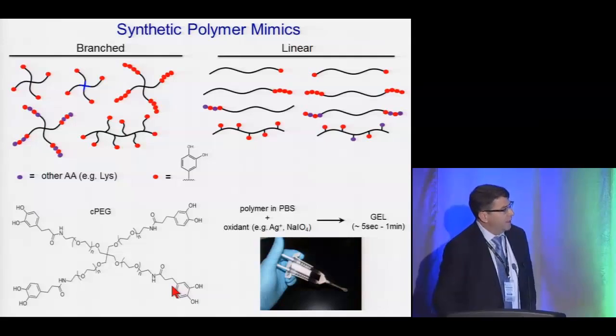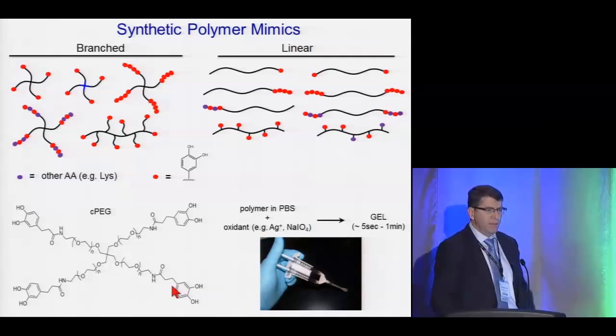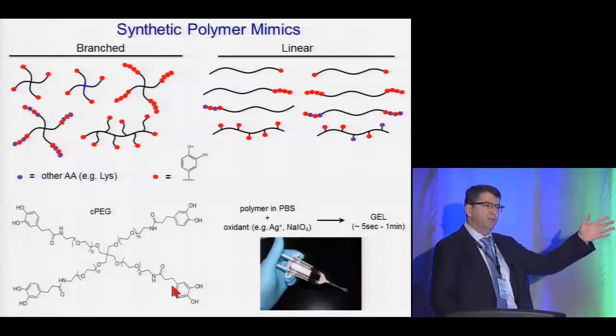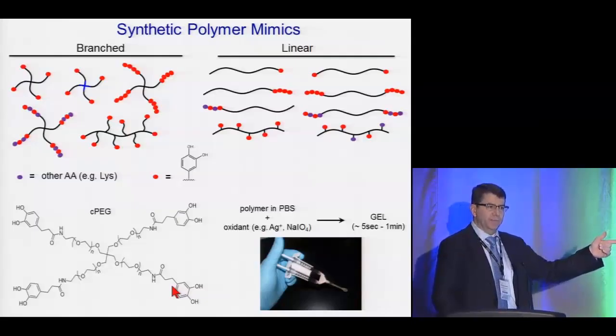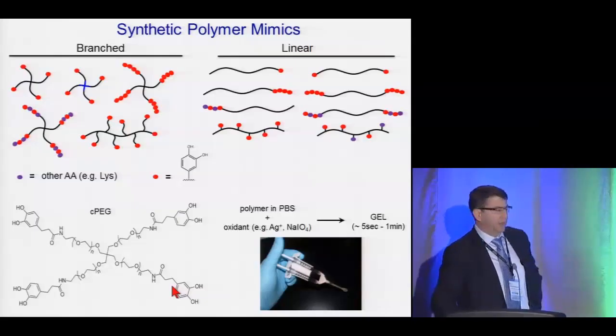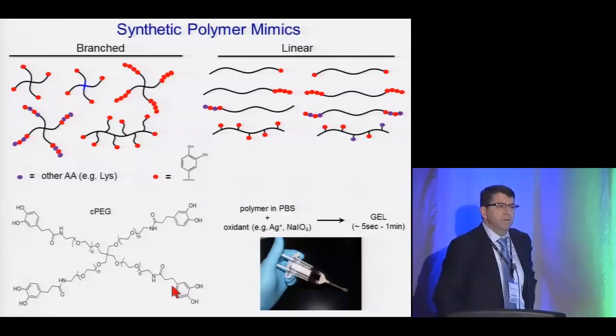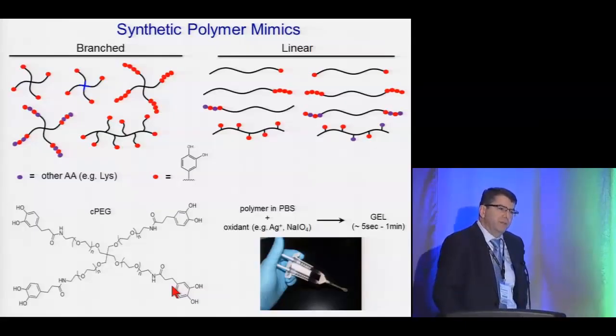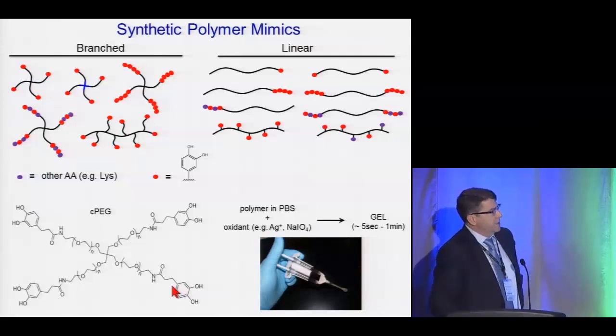However, in the presence of the catechol in this polymer, we have all the chemistry, as I've described, to do two important things with medical adhesion. One is to drive a solidification reaction from a liquid precursor, as a liquid medical sealant, to a solid, and do that rapidly. And then the other chemistry, as I've described as well, is that once oxidized, these can interact very strongly, covalently, non-covalently, with tissues, inorganic tissues as well as organic tissues. Okay? And this polymer can be formulated into a medical sealant using a conventional two-barrel syringe device, polymer in one, oxidant in another. They mix in a chamber here, come out as a liquid and gel in a few seconds or a minute.